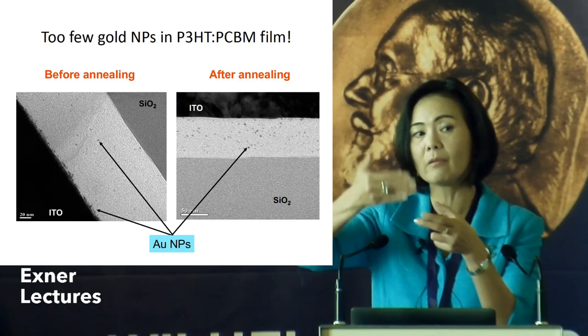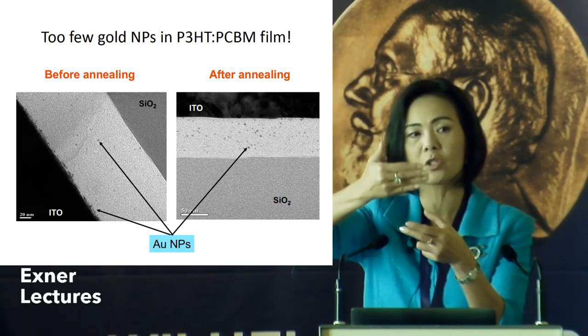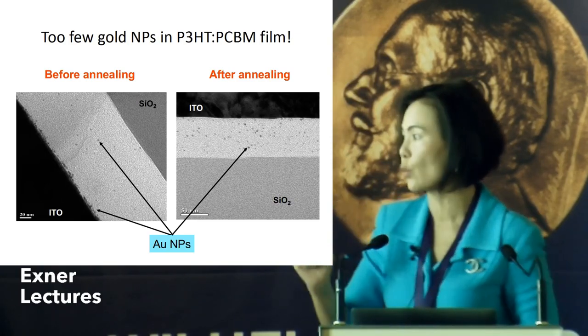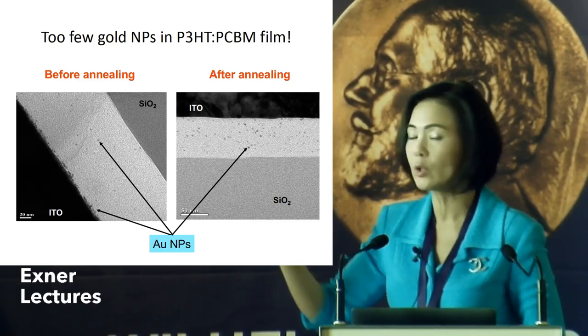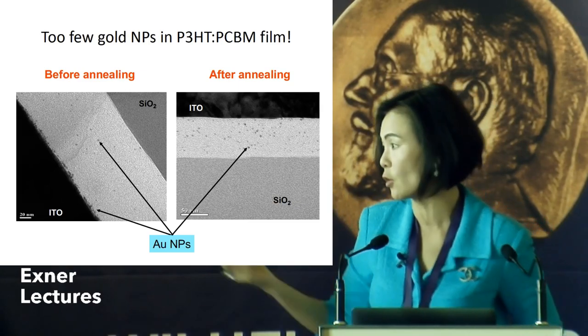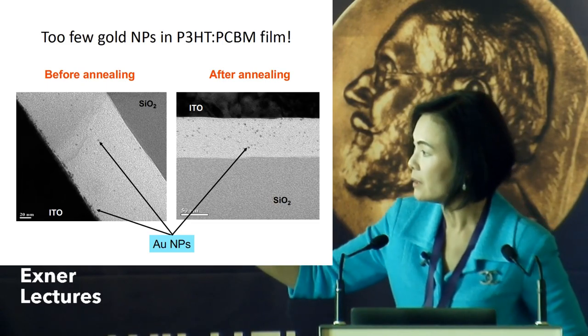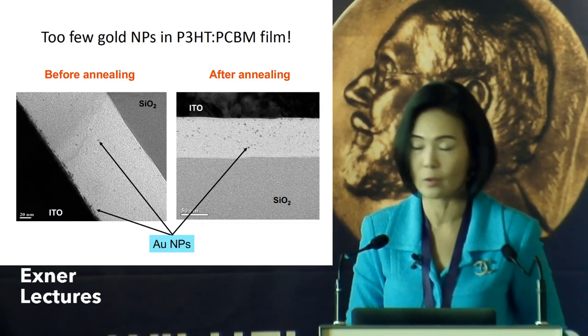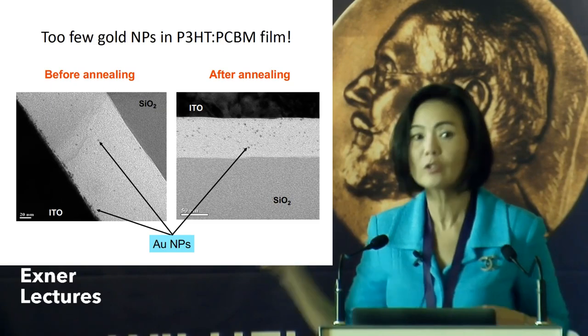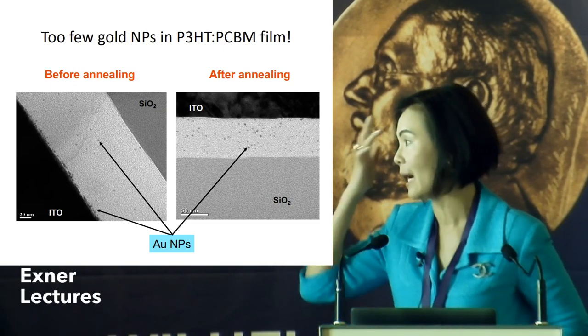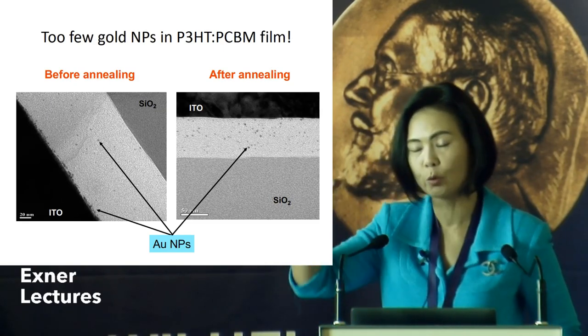So here I take the device, I cut using focused ion beam, I cut a thin slice through it, I flip it over, and I look at transmission electron microscopy, the TEM. And you can see the black dots are gold nanoparticles. So to our surprise, there are not that many gold nanoparticles in our active layer that give rise to almost double